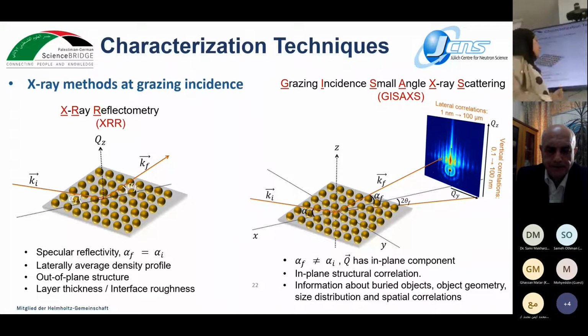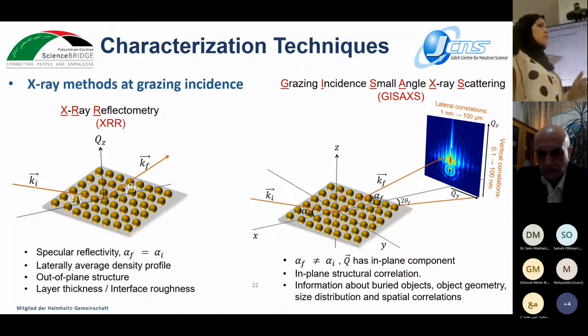But for the GISAXS technique, as I said, the scattered angle is not equal to the incident angle, and we end up with an in-plane component, where we get in-plane structural correlation, information about the object geometry, size distribution, and spatial correlation. So from GISAXS, we can get information about lateral correlation from 1 nanometer to 100 micrometer, and for vertical correlation, 0.1 to 100 nanometer. So, from X-ray reflectometry, we can get information about the correlation perpendicular to the surface, while from GISAXS, the in-plane one.